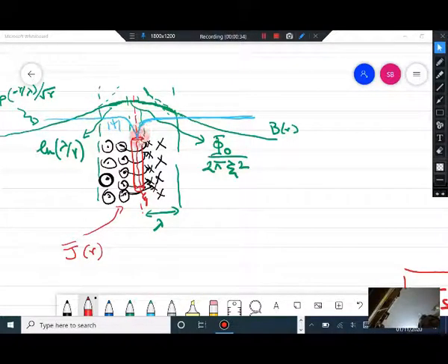The form of the decay of this order parameter is tanh(x divided by square root of 2 times xi), which we have already derived earlier. For a normal-vacuum interface, we had shown how the order parameter goes to 0. This is the same way the order parameter goes to 0 inside the vortex core.